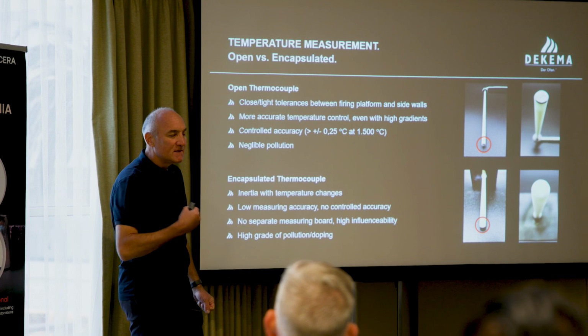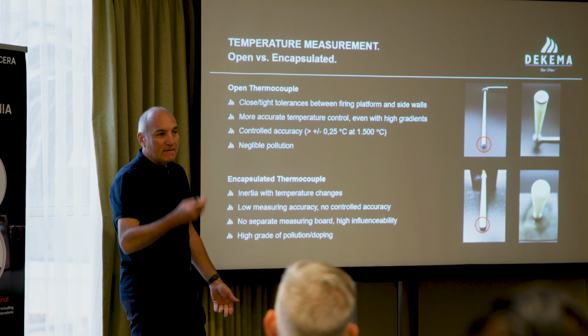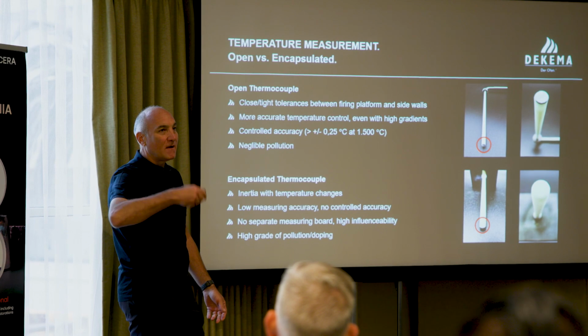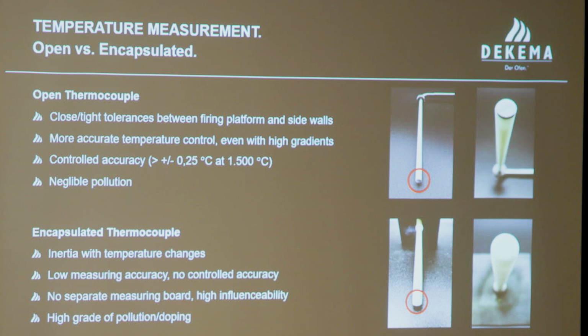Just imagine you have a fast sintering cycle. You want to sinter some materials. You have a 24-minute cycle with a DEKEMA furnace, and rising temperature. You start at 1,000 degrees. You go up with about 100 degrees per minute. Stay for 8 to 10 minutes, and then you just cool down. With this temperature rise, you must not go over the peak. You have to have a real flat curve with the temperature. You don't stress the zirconia material even more, which you already stressed through the short cycle.